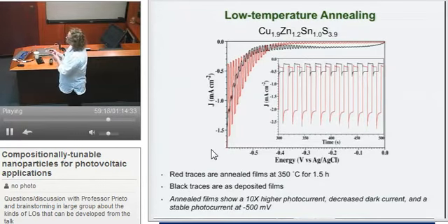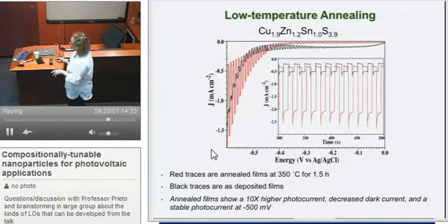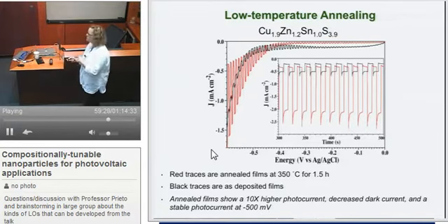When we heat it, you see the dark current goes away, and the photocurrent is much higher, and it's much better over time. So this inset is a constant potential, and we're just turning the light on and off. And you see that this compound is actually producing about a 10 times higher photocurrent after you heat it, and it's pretty stable over many cycles.